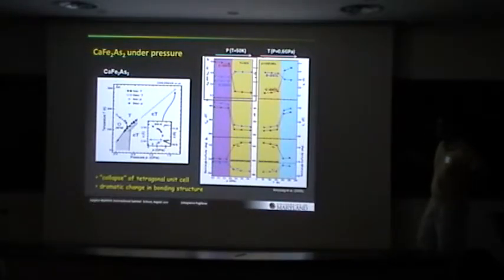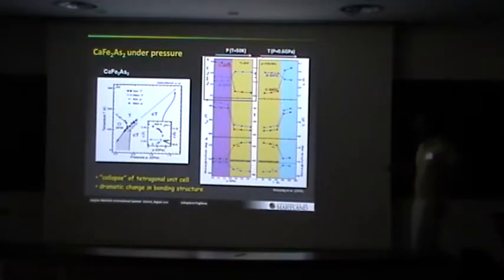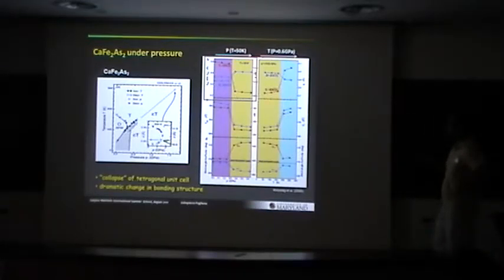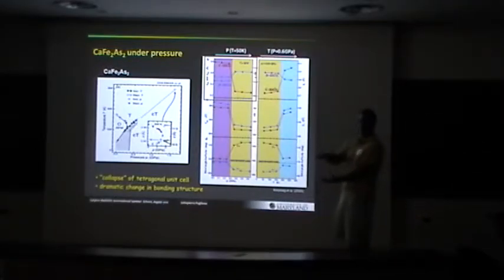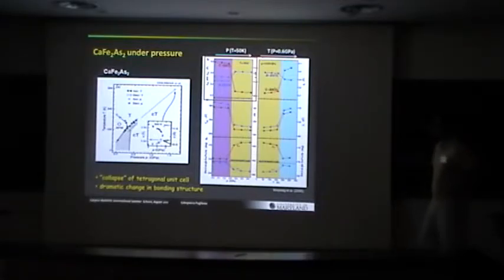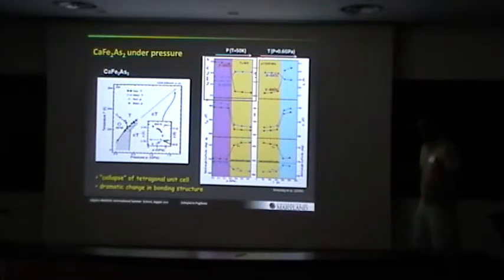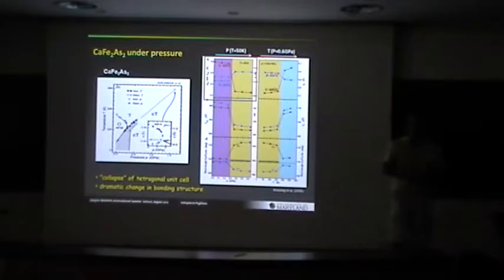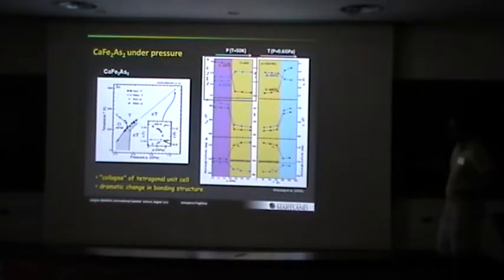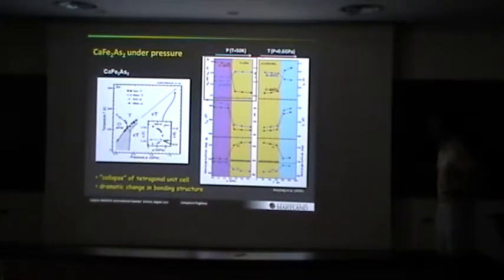Now this is C-axis unit cell and A-axis unit cell versus pressure. This is at 50 Kelvin. Just pay attention to the C-axis here. This goes from 11.5 angstroms at about 0.3 gigapascals, which for you guys that don't know is a quite small pressure, 3 kilobar. It's very easily obtainable. And this jumps by almost an angstrom. So the unit cell shrinks by 10% on the C-axis. Okay, A-axis actually goes up a little bit by maybe 1%. It's a much smaller change. The volume actually changes. The internal coordinates and so on change, as you might expect for such a drastic phase transition. So what happens is you suppress this magnetic order and then suddenly you run into this collapse transition.